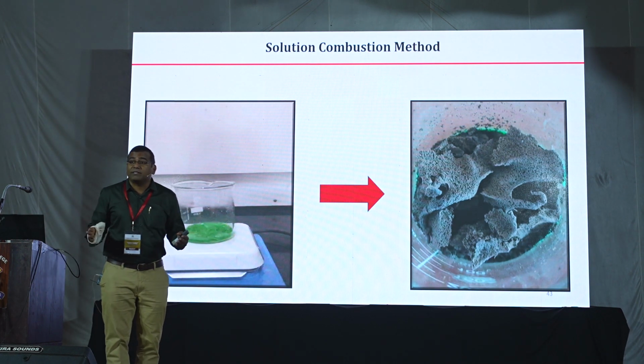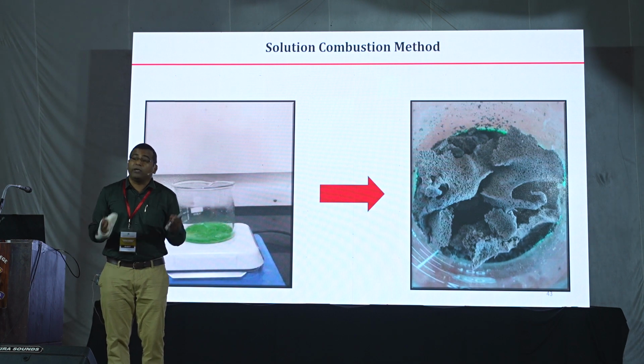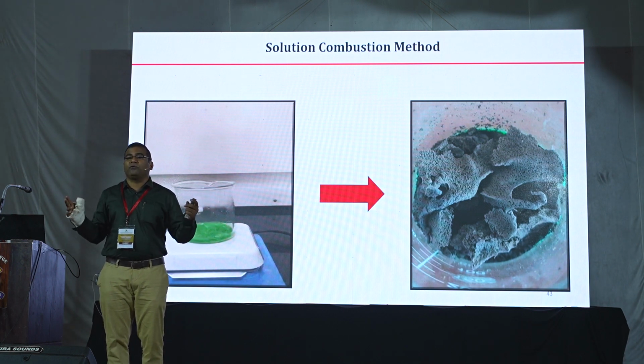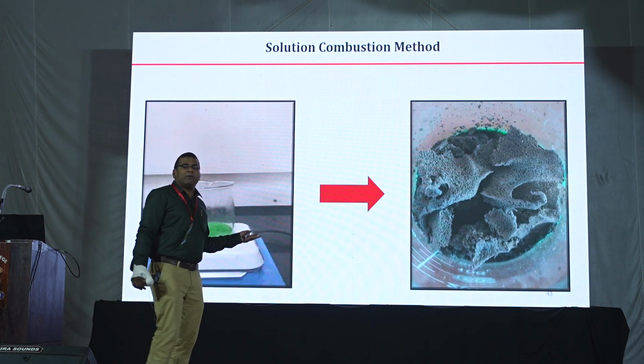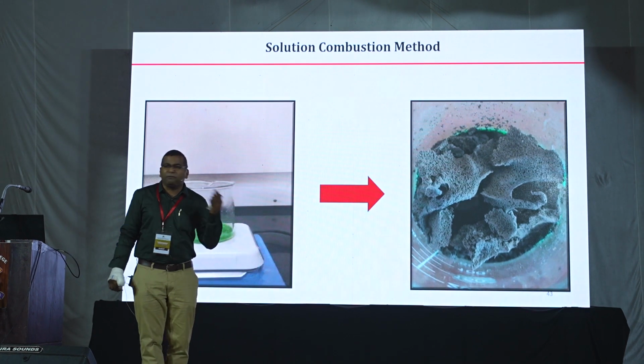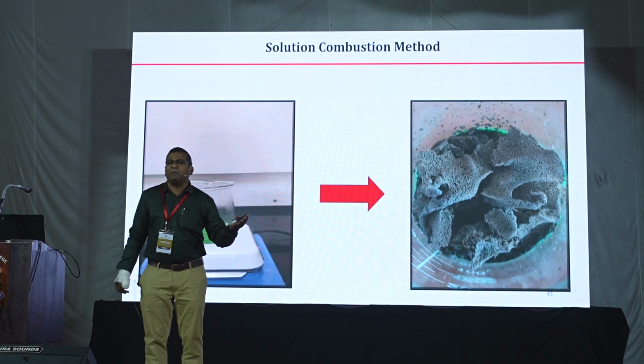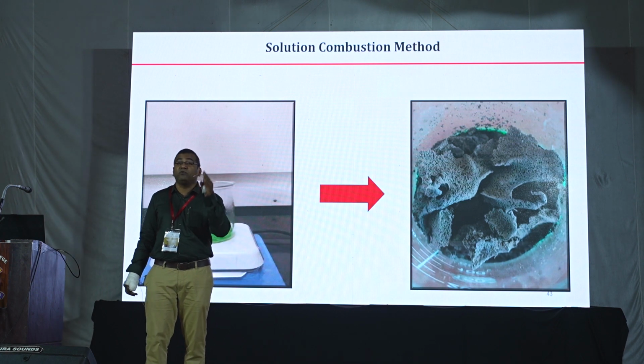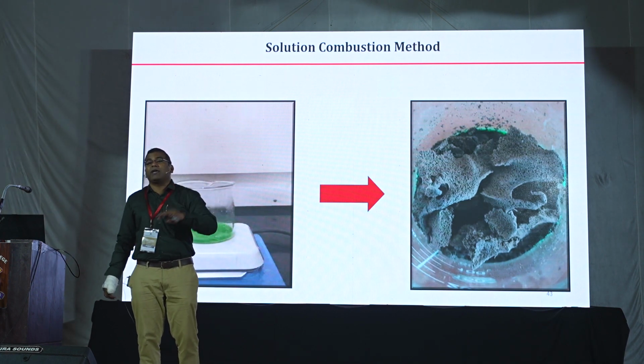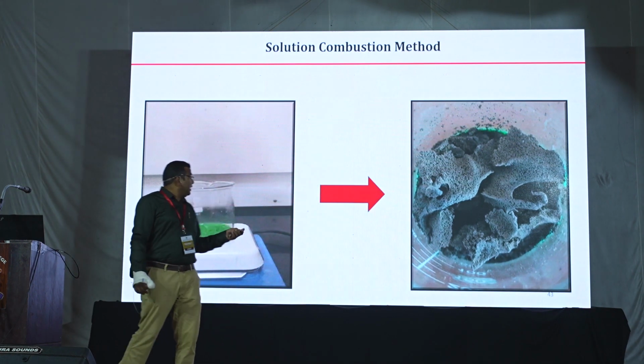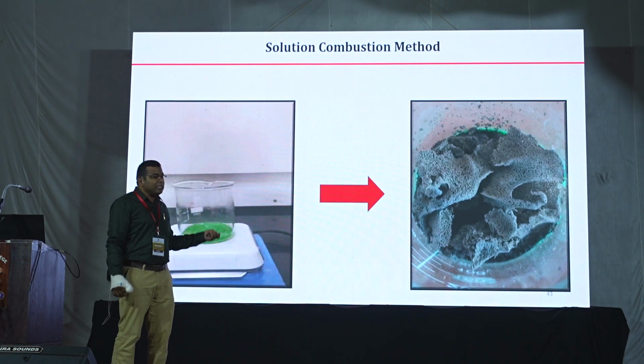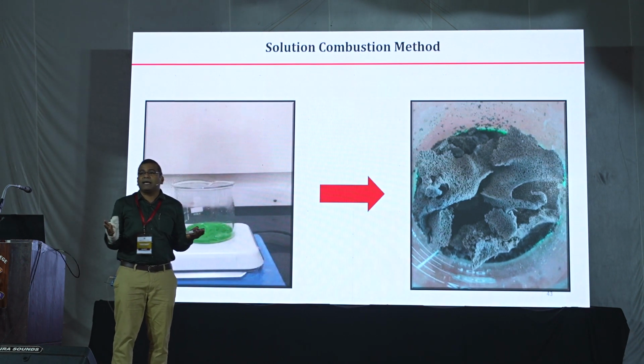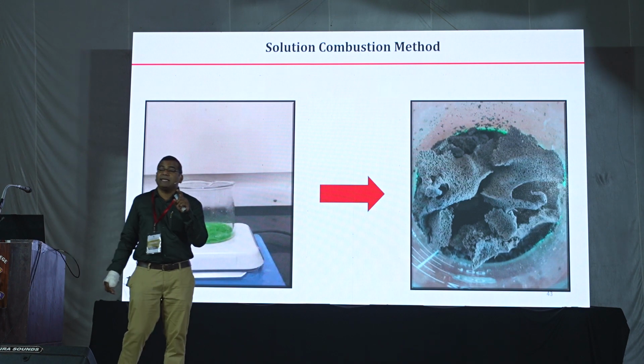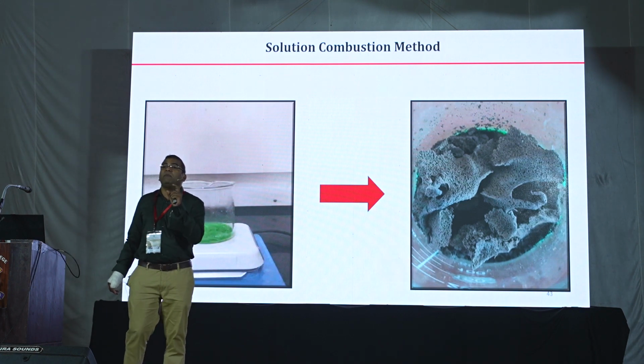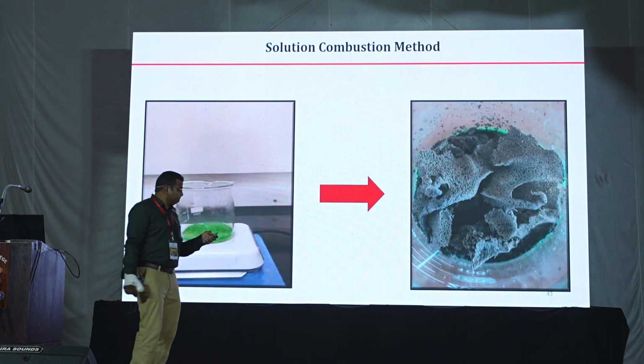We have almost 20 plus fuels like urea, glycine, and so on and so forth. But the variety you can bring there is that if you change the fuel, you can have a lot of variation in the materials. If you change the fuel to oxidizer ratio, you can tune many things. So these kind of nice porous materials you can make, and the synthesis time is just 2 minutes. In 2 minutes you can get a complicated material.